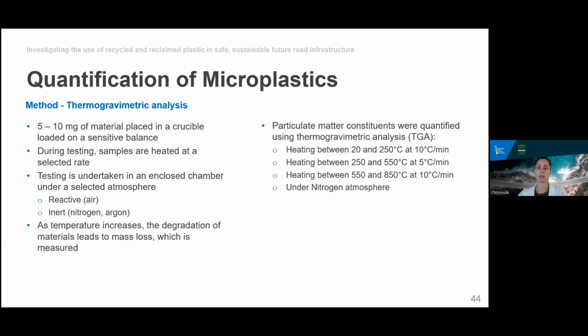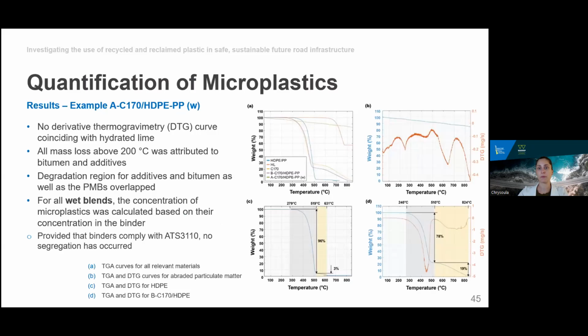As the samples are heated, the bitumen and plastics degrade, leading to mass loss. So in the image to the right, you can see an example of the mass loss and derivative curves generated by this method. As the aggregates are not expected to degrade within the temperature range used in this analysis, all mass loss above 200 degrees Celsius was attributed to the degradation of bitumen and plastics.